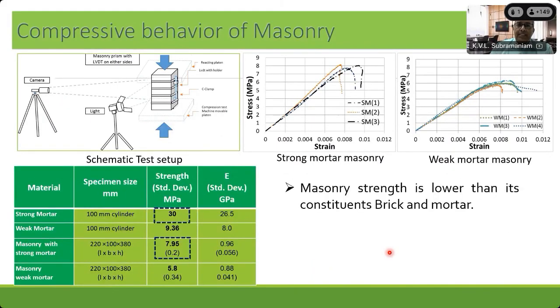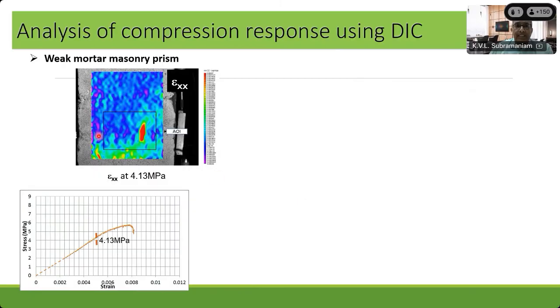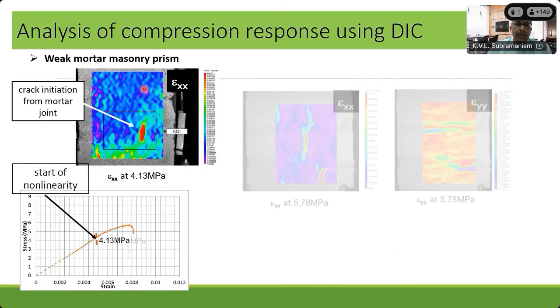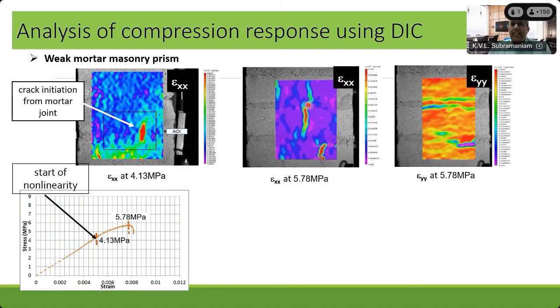So now, if you look at it, what happens? This is the interface between the brick and the mortar. The crack starts right here. That's where the tension is in the mortar. The mortar splits first, and then that drives the crack into the brick. The crack then grows, and you get splitting of the masonry. Basically, everywhere the mortar is in a state of biaxial tension, or in tension in the plane of the joint. So in this plane here, the mortar is in tension, and that causes splitting of the mortar, and that induces cracking in the brick.